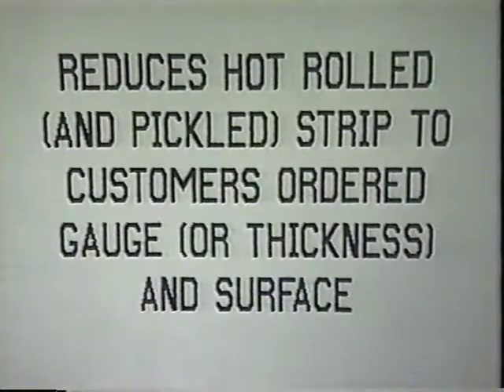We also start to make the surface. In the cold reduction process, you need to have a surface which later on can be temper-rolled with a matte finish. So you start that process here. If you don't do it right, you can leave many blemishes here on the tandem mill, so that it's unacceptable. You've got to have a good strip surface coming out of here with respect to mechanical marks, and the right texture coming out of the tandem mill for subsequent surface texturing for exposed applications, what we call matte finishes. But the primary thing here is to make thickness.